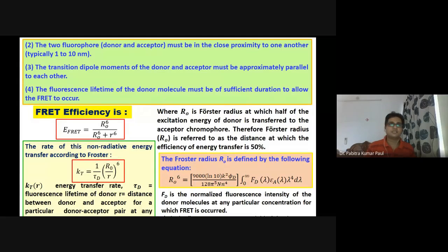Here basically capital R0 is the Förster radius at which half of the excitation energy of the donor is transferred to the acceptor chromophore. That is, 50% of the energy should be transferred, so that the energy transfer is 50%. And this is basically measured by steady state fluorescence measurements. You can easily measure the steady state fluorescence intensity by simply measuring the intensity of the emitted radiation from the donor molecules only.